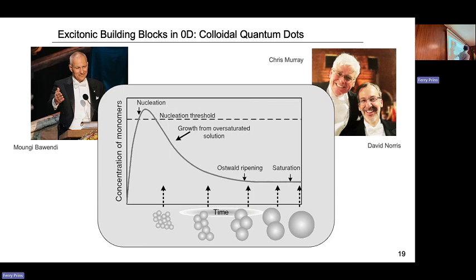Then you reach a point—it's more technical and I don't want to go into that because I'm not a synthetic chemist—you have a process that is Ostwald ripening, where actually they call it size focusing as well. So smaller particles dissolve again, but bigger particles are already stable. So there's a process where smaller particles dissolve and then grow again on the bigger ones, which focuses the size at the end, until you reach saturation. Like this, you can control the size.